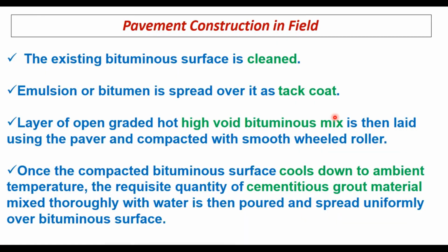For pavement construction in the field, the steps involved are that the existing bituminous surface is cleaned. Then above that, emulsion or bitumen is spread over it as a tack coat. A layer of open graded hot high voids bituminous mix is then laid using the paver and compacted with a smooth wheeled roller, as we generally do for a BM layer. Once the compacted bituminous surface cools down to ambient temperature, the requisite quantity of cementitious grout material mixed thoroughly with water is then poured